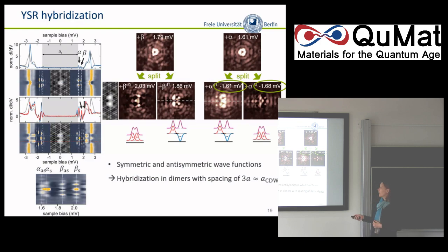Okay, good. A minor, or no, it's not a minor detail: we always look at the shapes, and we stared at them to find the similarities. I said that there's always the electron and the hole part, but the patterns of the electron and hole parts look different. So we can also follow from the shape whether a state is on one side, at positive energy or negative energy. And here we see that there is actually a change in the side where they are.